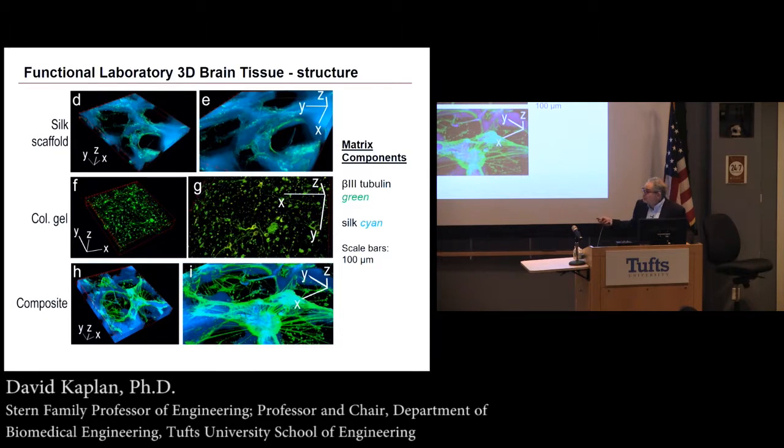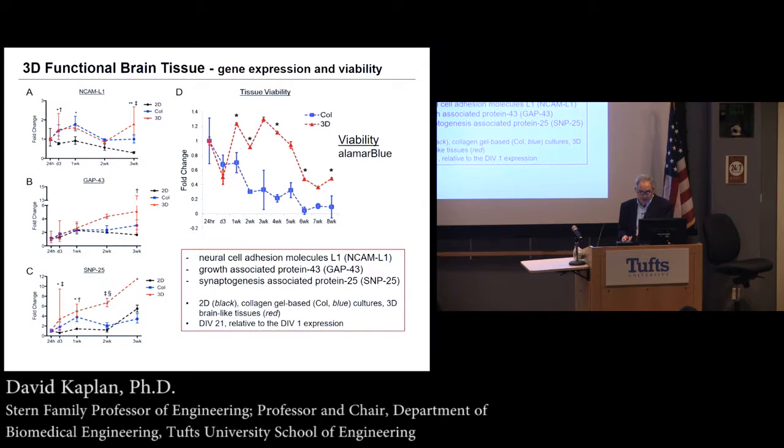And if you only use the collagen gel, and this was mentioned a little bit even in the first talk, collagens are wonderful, but they are not very stable materials in vitro culture. They tend to contract over time. And so the cells get in there, they're alive, but they don't really send out projections. So they're sort of in steady state, not doing much. They're not going to give you a functional model. And then if we go to the composite system, which is taking the porous sponge in combination with a gel, now we get the best of all worlds, and we have a functional set of structures we can start to at least pretend look like a brain structure and go on from there. So the designs are really important if you're looking for a physiologically relevant set of outcomes.